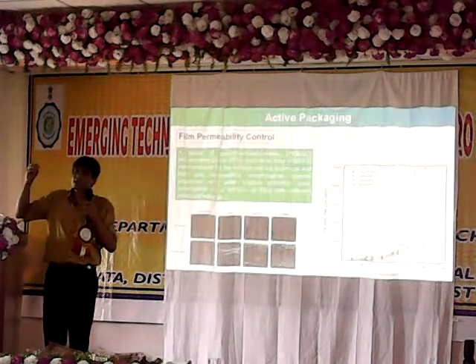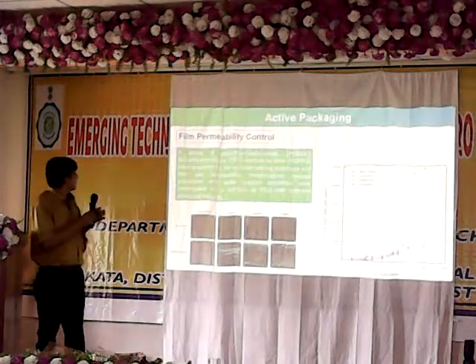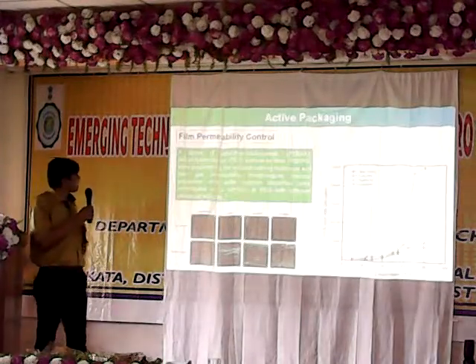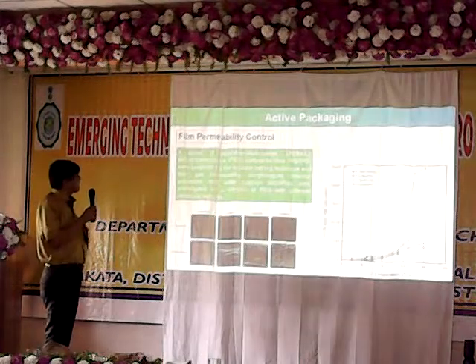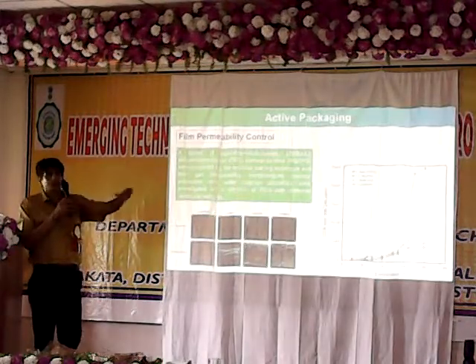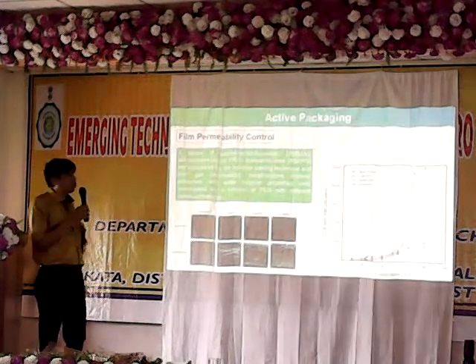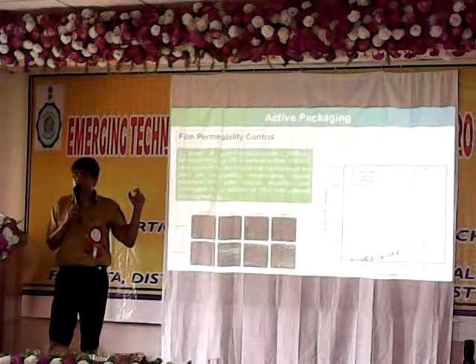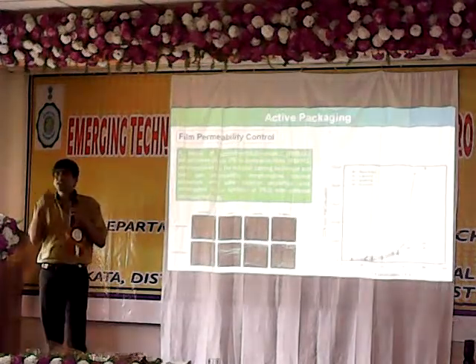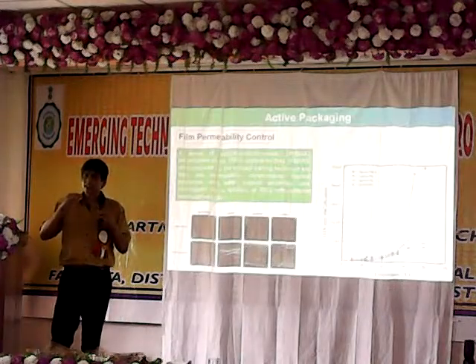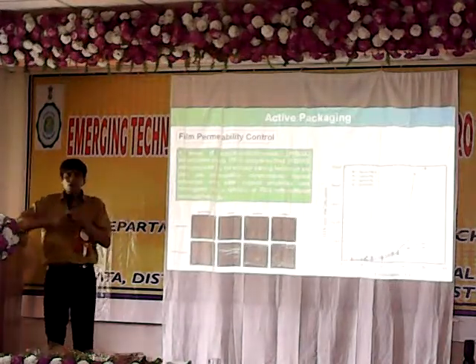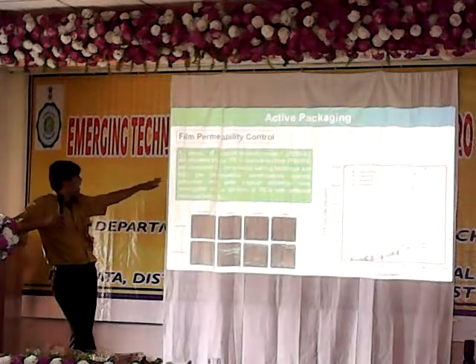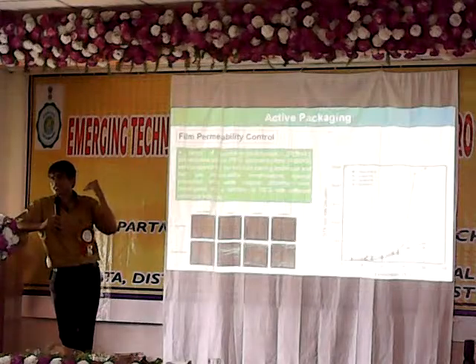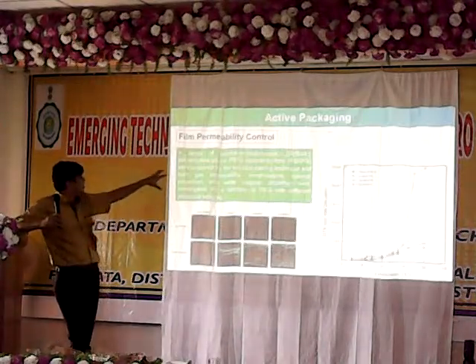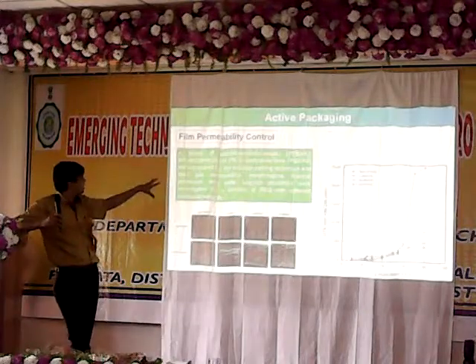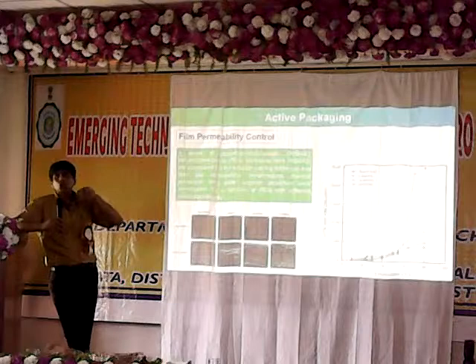There are films where we can use side linkage, like one example is polyether block amide, called PEBAX. This particular film is the supporting material on which we use polyethylene glycol. Polyethylene glycol is a phase change material. It changes its phase at different temperatures. Similarly, like PEG, polyethylene glycol, we have many other materials which change phase at different temperatures. Now, what we think is PEBAX is put along with PEG to form a composite.